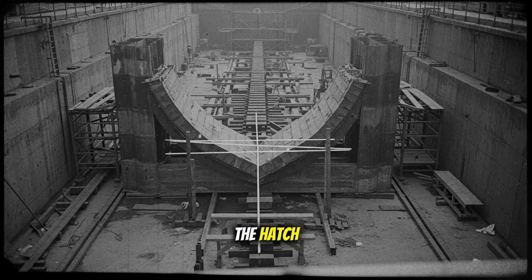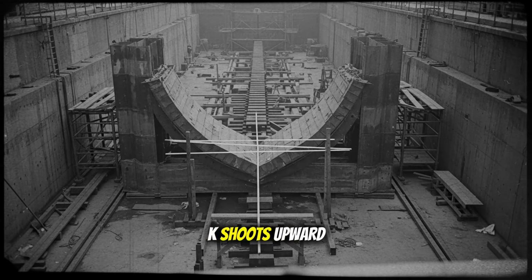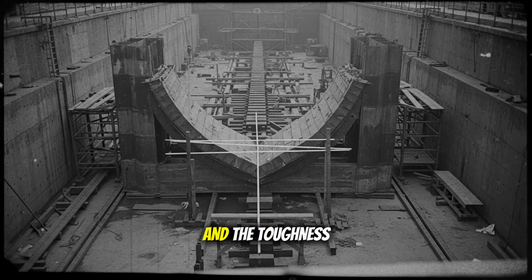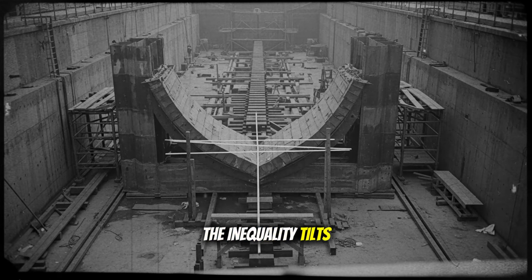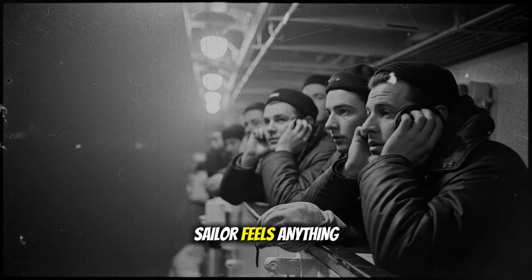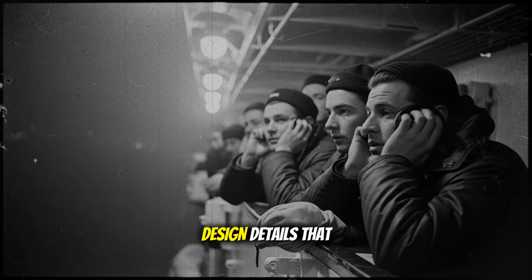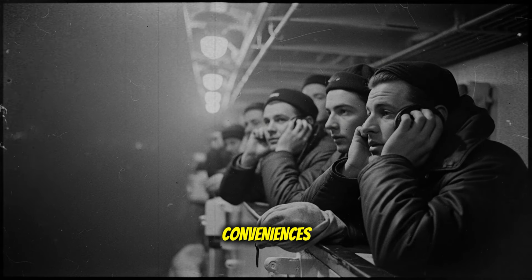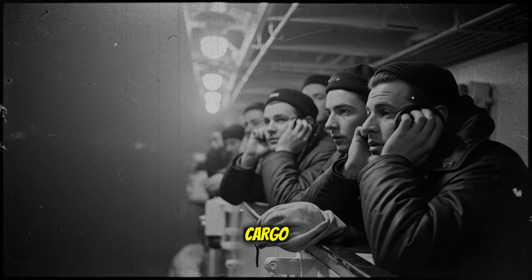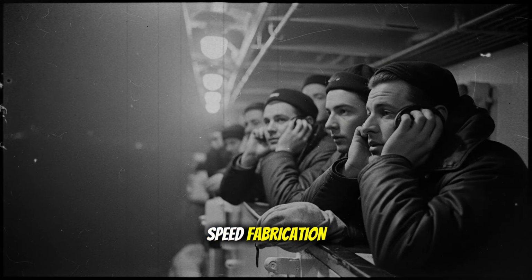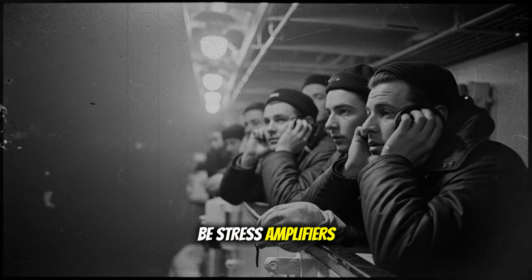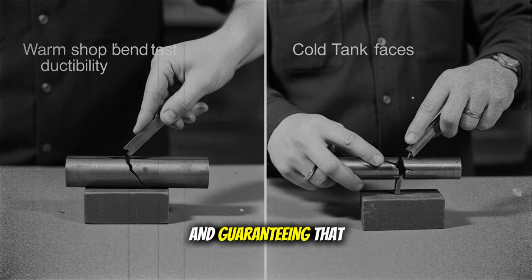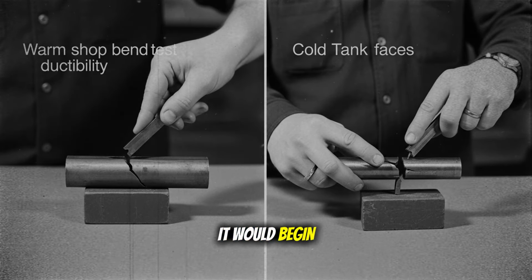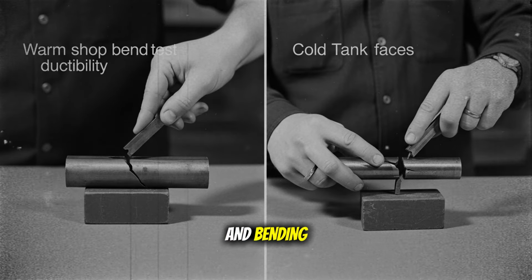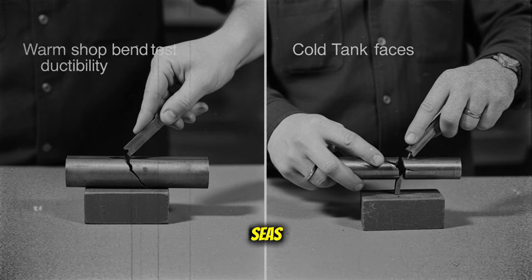This thinking placed the hatch corner and the weld toe under a microscope, because in those places Kt shoots upward, and if the sea is cold and the toughness low, the inequality tilts toward failure long before a sailor feels anything under his boots. Design details that once looked like conveniences, rectangular openings for cargo, snappy cutouts to speed fabrication, turned out to be stress amplifiers, multiplying local loads and guaranteeing that if a crack began, it would begin there, especially under torsion and bending as the hull writhed in heavy seas.